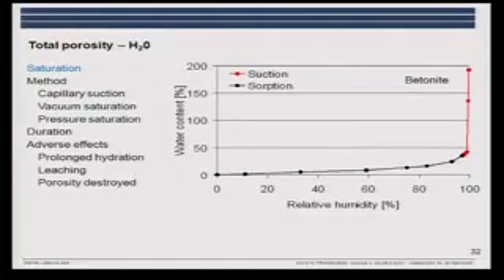But it illustrates that if we are just having absorption and capillary condensation, we are able to fill the sample according to the black curve. Whereas if we apply suction and pressure, we can actually fill more of the pores, the larger pores. But we do not have condensation in the larger pores. So therefore, we need another technique.